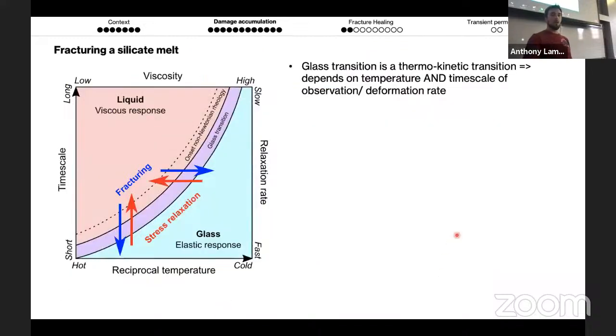So a quick explanation of how silicate melt mechanics work: silicate melts are really good at forming glass. And glass is important for volcanoes because depending on how fast you deform the magma, you can fracture it by going too fast. You can cross the glass transition, or if you change the temperature, if you go from hot to cold, you can fracture it as well. Same as what we've seen for the columnar joints.